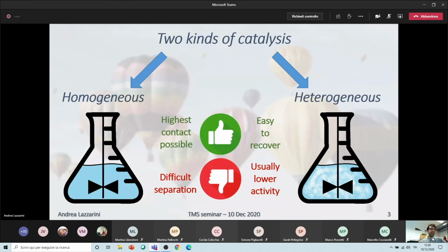So the drawback, as you can imagine, for the homogeneous phase is that you have a difficult, if not impossible, separation between the catalyst and the reaction phase, which makes them often not reusable as catalysts. Heterogeneous catalysts, in general, show lower activity than the homogeneous counterpart, just because having two different phases, you have a reduced contact possible between the active phase of the catalyst and the reaction environment.